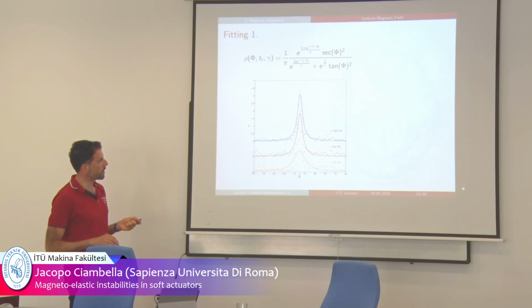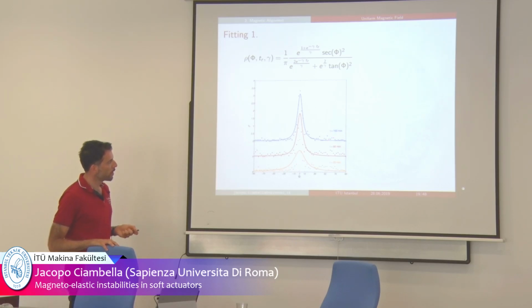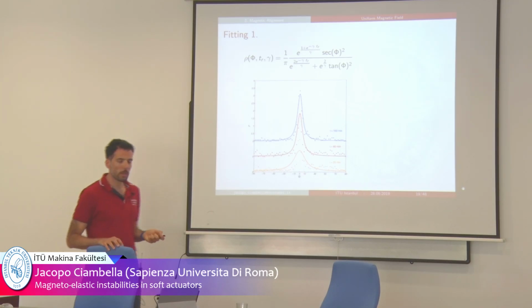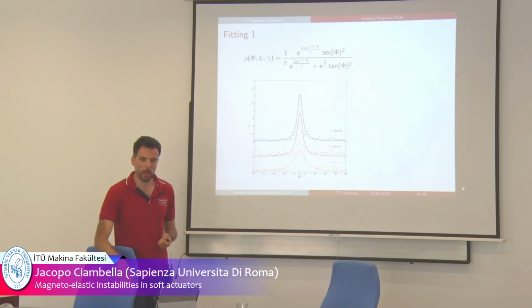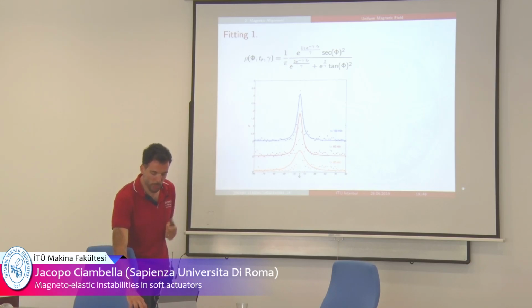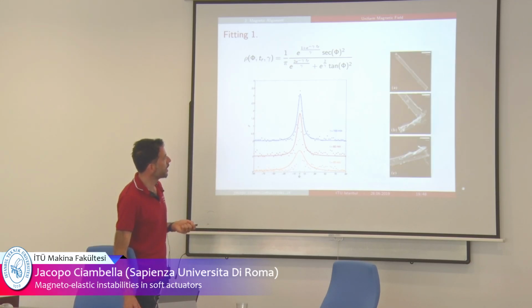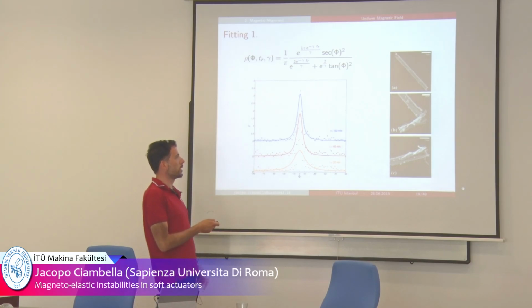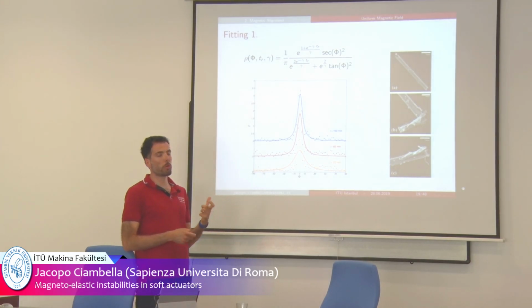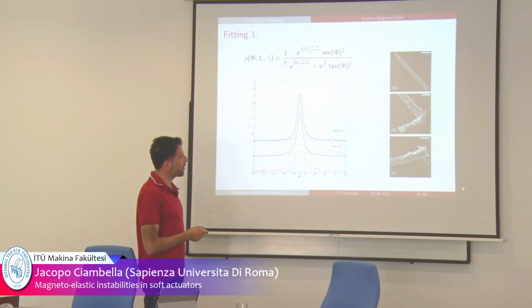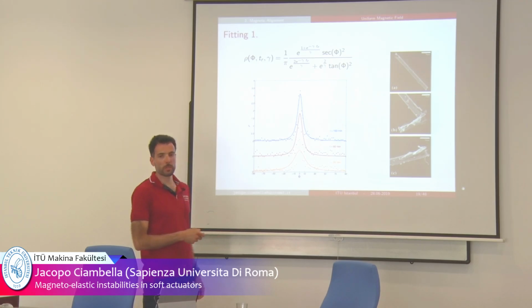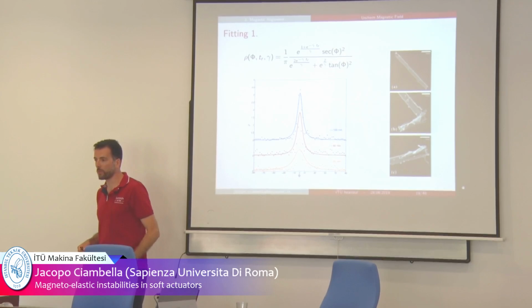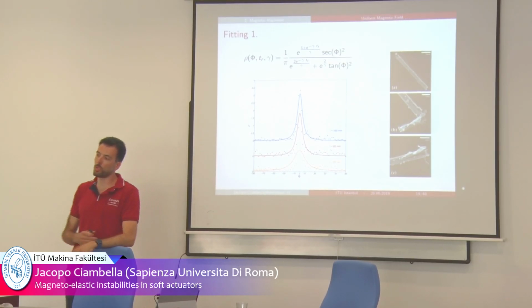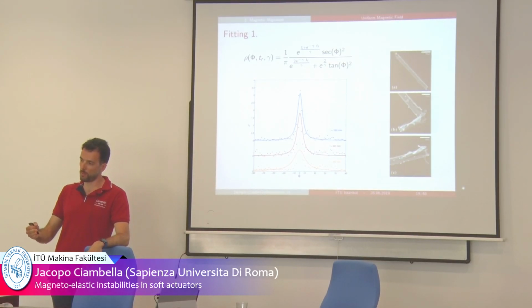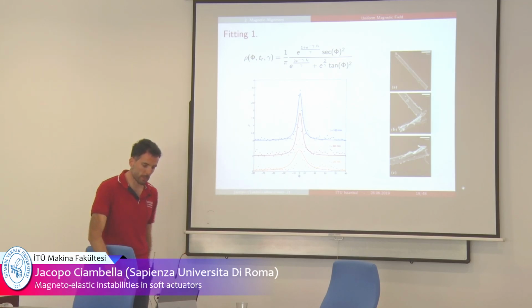So as expected, the shape of this curve increases, so more particles are orienting around 0 degrees, but not all of them are. Why so? We asked ourselves why, and this is what we thought is happening. Due to the processing of this fiber, many fibers were broken and many fibers lost their coating. And if they lost their coating, it means that you need to apply a much higher field to orient them. And so this is our explanation.